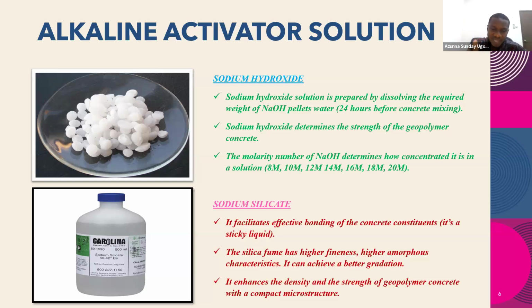The two basic things that affect the setting of your geopolymer concrete are the content of the calcium oxide in your binder and the molarity of your sodium hydroxide. That is what affects the setting time. It shortens the setting time actually. So if you use a molarity of, say, 20 mole, your setting time is going to be very, very short, because the water content will be very small, and then the reaction is going to happen much faster. Even in less than 5 minutes, your concrete could become solid. That is why you're not advised to use a molarity of sodium hydroxide that is too high.